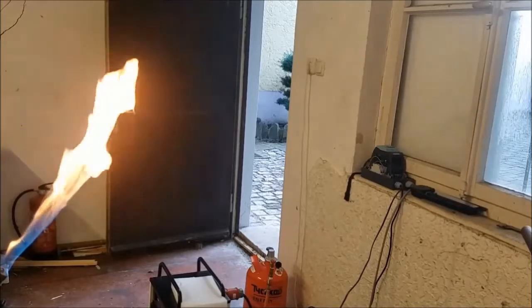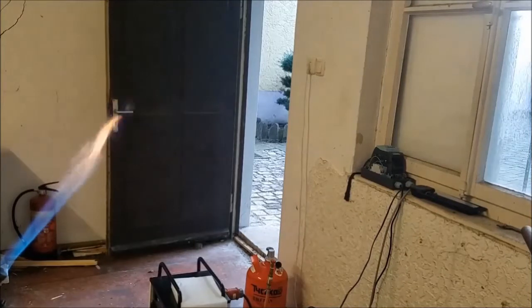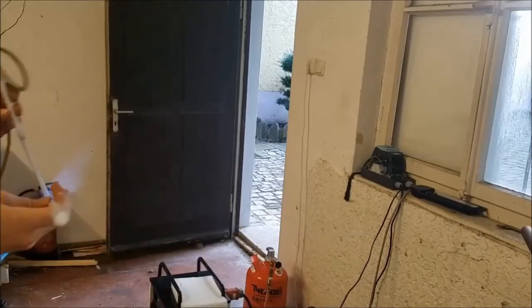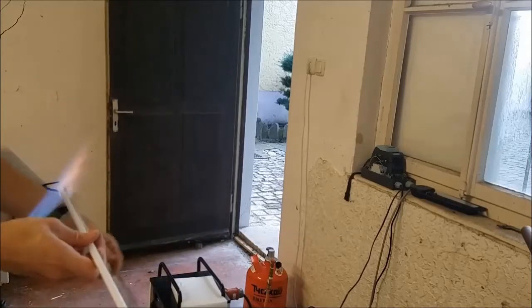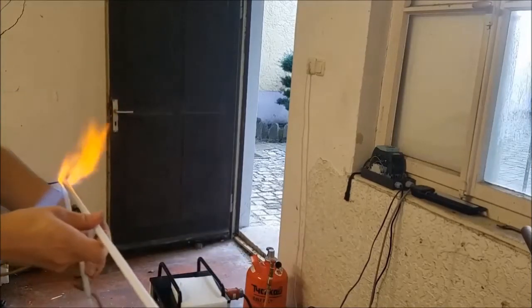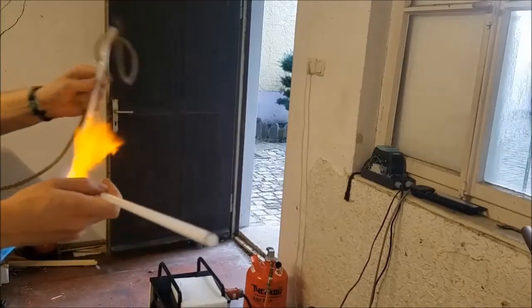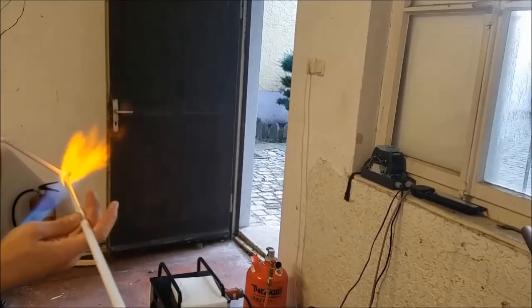So many American shops use a wire mesh. I think it's a brass or stainless steel mesh. I have made the experience that my paper still starts to burn when I use mesh. So I switched. I saw in a Japanese video that the Japanese like to use mica, so I switched to that. The problem with mica is that when you put the hot glass on it, it also warps a bit and pushes your tube a bit up from the pattern. But this is the solution I have by now, so I'm using mica and that heat resistant cloth on the table.